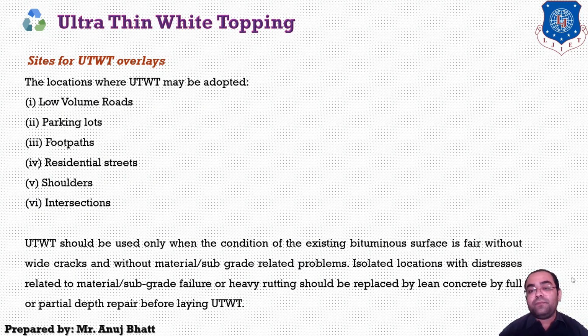Well, ultra thin white topping should be used only when the condition of the existing bituminous surface is fair, without any wide cracks and without any material related problems. Isolated locations with distresses related to material failure or heavy rutting should be replaced by lean concrete, by full or partial depth repair, before the laying of ultra thin white topping.